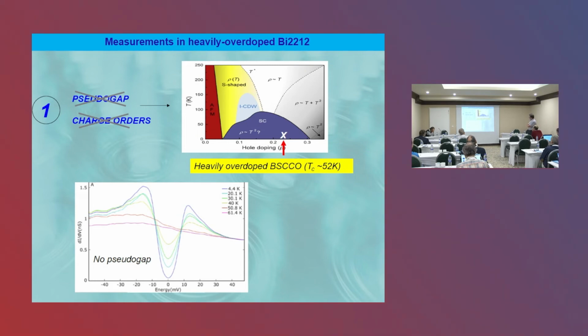Okay, so the recent measurements we've been performing were focusing on the portion of the phase diagram where the pseudogap and all these charge density wave modulation were absent, seen by other techniques. And so we focused on the heavily overdoped BSCCO crystal, where the Tc is 52K, and obviously if you make the temperature-dependent measurements, you see that above Tc there is no sign of pairing, of opening of a gap. So there is no pseudogap as expected in the compound I will show you now.